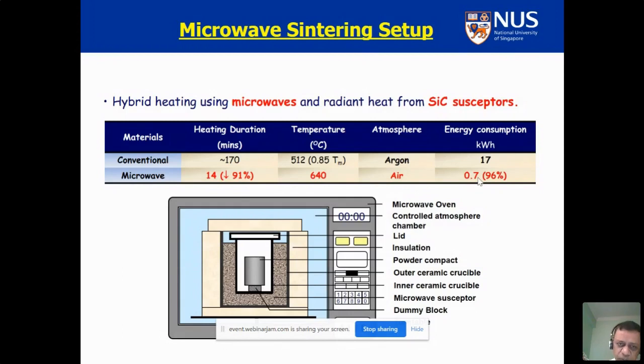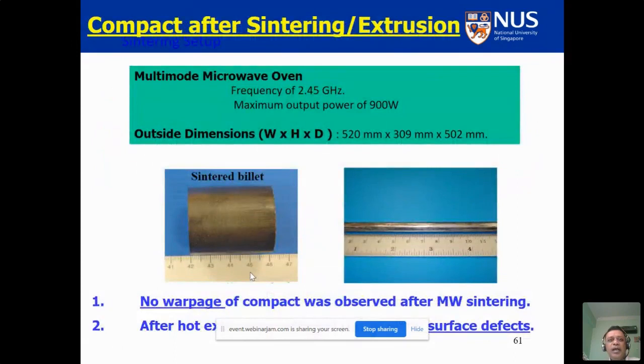So how the microwave works is that when you switch on, the microwaves are absorbed by the metallic compacted billet and heat the billet from inside to outside. And this susceptor, which is silicon carbide particles, heats the billet from outside to inside. So you have two heat fronts, inside to outside and outside to inside. And that is what leads to the energy efficiency. So you can see how the microwave comes in and how the billet can be heated in a very, very quick fashion. And as I say, it's a normal household oven, and you can get the sintered billet, you can extrude it, and we don't see any issues with that.